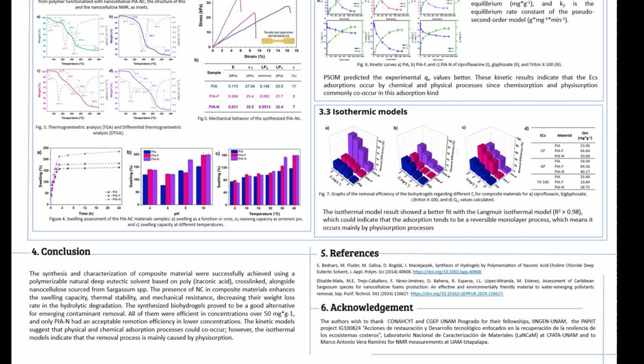In conclusion, the synthesis and characterization of composite material were successfully achieved using a natural deep eutectic solvent based on polyitaconic acid, mixed with nanocellulose sourced from sargassum. The presence of nanocellulose in composite materials enhances swelling capacity, thermal stability, and mechanical resistance. The synthesized biohydrogels proved to be a good alternative for emerging contaminant removal. All of them were efficient at concentrations over 50 mg per gram, and only the material with the nanocellulose from the second sargassum source has an acceptable removal efficiency at lower concentrations.